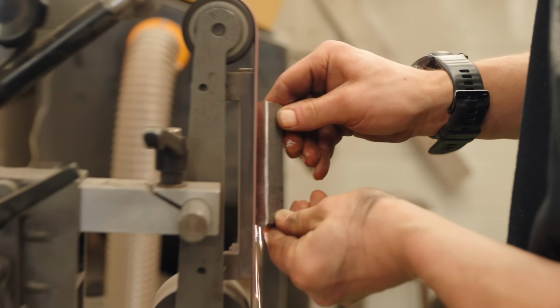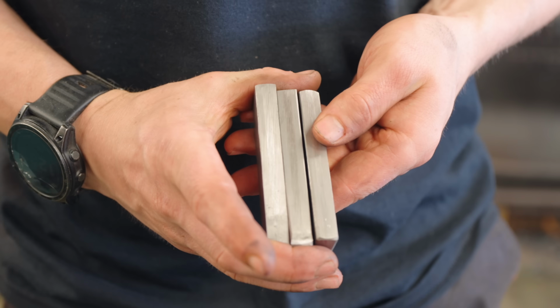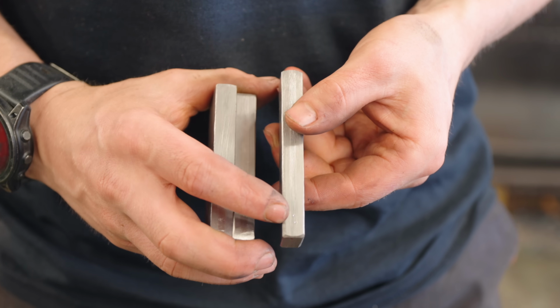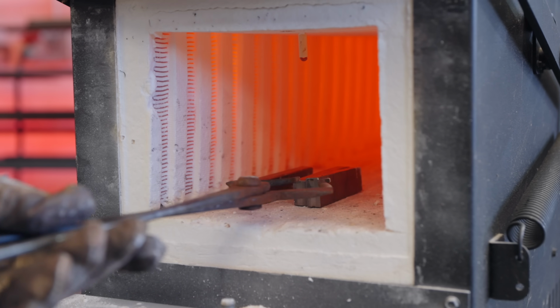Yeah, baby! These are our 3 samples to do some tests with. Gone ahead and hardness tested one of these. Comes out at 26 Rockwell in its unhardened, air-cooled state. With those 3 samples, the plan is as follows. With 1, we are going to oil quench it. We want to see if it will get hard enough, or if it splits apart and delaminates. 2, I'm going to take one out and simply air-cool it, see how much hardness we get from an air-cool, now that it's a slightly smaller cross-section.